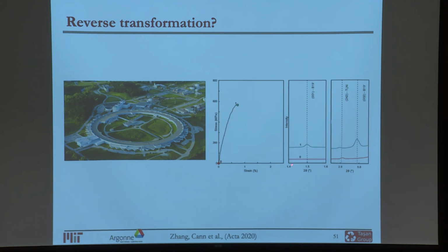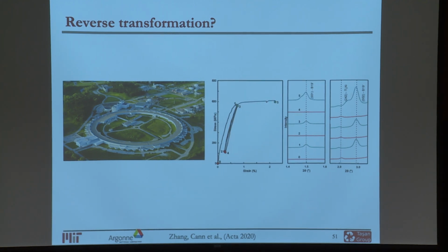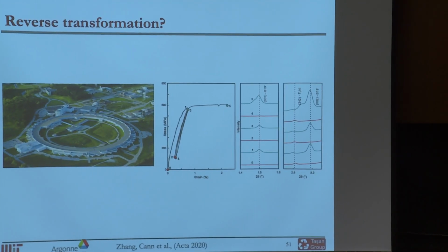And if you look at these couple of peaks, you can see new peaks forming. And then we unload. So you go from 1 to 2. You release the stress, and you see that some of those peaks are disappearing. And you can repeat this multiple times. It seems to work. That's nice. But if you get a little bit too ambitious and deform it too much, it doesn't work anymore.